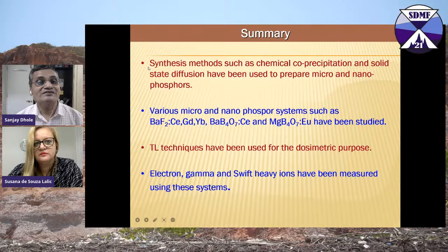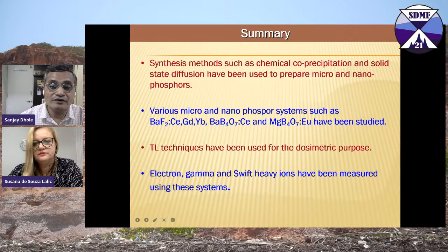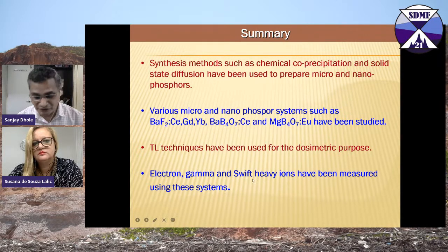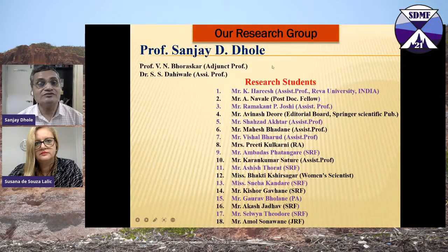So summary, synthesis methods such as chemical coprecipitation and solid state diffusion have been used to prepare micro and nanophosphors. Various phosphors that we could develop, that is three systems, can measure right from 0.1 gray to 4 kilogray or 10 kilogray or so. That is barium fluoride doped with cerium, gadolinium, ytterbium, and barium borate doped with cerium and magnesium borate doped with europium have been studied. TL techniques have been used for the dosimetric purpose, and electron, gamma, and swift heavy ions have been measured using this particular system.